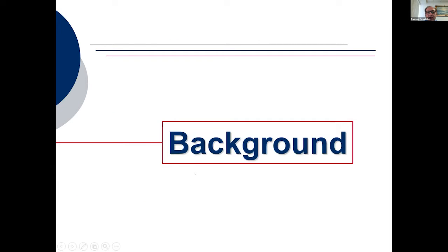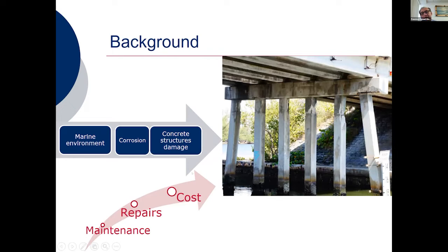A little bit about background. Here in Florida, we have a large inventory of bridges that are partially immersed. As you can see here, this bridge is close to our facility in Dania Beach, and it is about 60-something years old. You can see that there are several columns in distress at this particular location. Interestingly, there is not much corrosion, at least visually, taking place at the tidal zone or above it, rather in the atmospheric section in this particular situation.